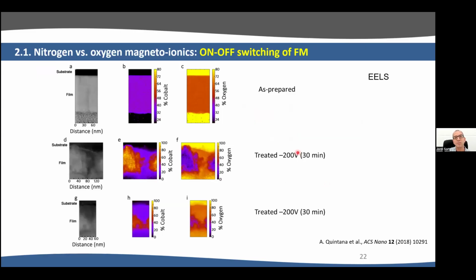If we have a look at the compositional maps obtained by EELS, you can see that the as prepared film is completely homogeneous. So this is the cobalt mapping, this is the oxygen mapping. Everything is homogeneous, but after treating with a negative voltage, we see some regions that are becoming enriched in oxygen and some regions that become enriched in cobalt, quite often following this direction perpendicular to the film. And this is because these grains in cobalt oxide are columnar, and the ions prefer to move along the edges or the boundaries of these grains, so perpendicular to the film.